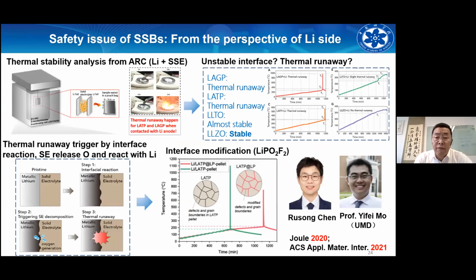And in order to improve safety, a solid-state electrolyte used in batteries will definitely be a very effective strategy. But this does not mean the application of a solid electrolyte automatically gives intrinsic safety. So our group collaborated with Professor Yifei Mo from UMD, US. We understand that LATP and LAGP will react with lithium at the anode side, leading to a similar thermal runaway. Of course, the T1 temperatures are 200 degrees C and 300 degrees C, much higher than for the liquid one, but you still have thermal runaway. However, LLTO and LLZO do not have thermal runaway behavior. So even among oxide electrolytes, some are safer and some are not. This should be carefully selected in the future when designing solid-state batteries or hybrid solid-liquid batteries.